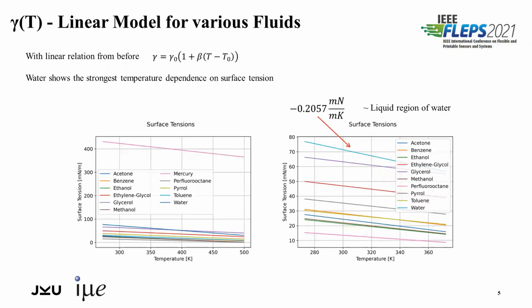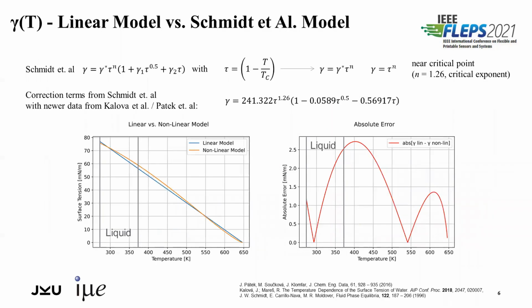If we now plot this linear relation between the surface tension and the temperature for all the liquids listed in the table, we see that water shows the highest dependence of its surface tension on a change in temperature. So gamma gets generally lower with rising temperature. And gamma's unit is millinewton per meter, so the change has the unit millinewton per meter per Kelvin. The right-hand side figure shows the same data as the left-hand side figure, but without mercury and only in the liquid region of water. There is also a nonlinear model from Schmidt et al., which I show here as a comparison.